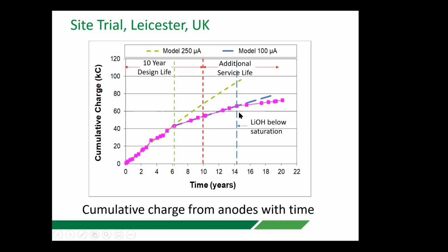And then we had a third deviation, but we were able to work out that deviation as when the lithium hydroxide, saturated lithium hydroxide, had diminished, and therefore there was no longer a saturated amount of lithium hydroxide, and the pH started to drop. So that was due to the drop in the pH. But what was that reduction due to? Now, we've assumed since that it's because the corrosion products have actually accumulated to such an extent that they started tightening up the structure, and therefore the electrolyte was finding it more difficult to electromigrate and therefore resisted the current flow.